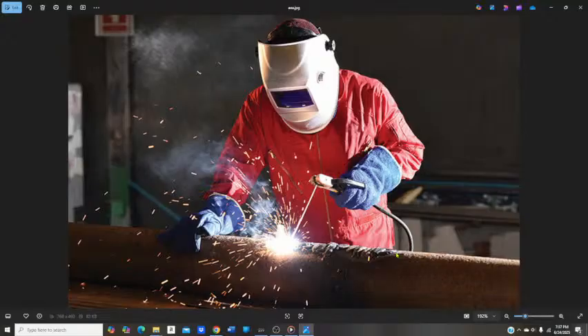And I could weld 1 inch plate to 1/2 inch thick 12 by 12 I-beams for the base plates for the structures for the buildings. And you could lay that with one single pass, and you could get a great weld bead out of it, and you just have to chip the flux off. If you use like a 70 series rod, a lot of times the flux will actually peel up for you. It's really cool how some of it will work.